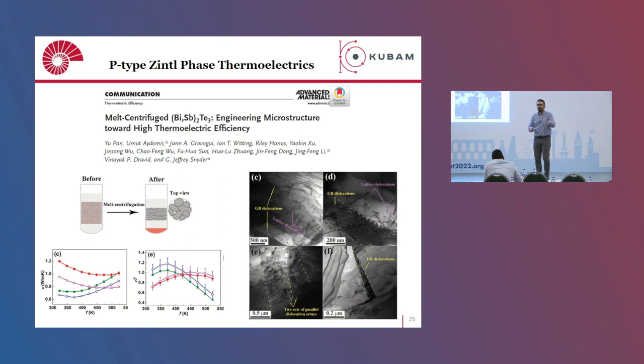So we knew that you can make this material p-type, but then we thought, how can we improve the thermoelectric efficiency, or what else can we do? So we applied what we call a melt centrifugation method to this material. We used this technique on bismuth antimony telluride, which is actually the best low-temperature material. The idea is that you intentionally add an element, for example tellurium, some excess tellurium, inside bismuth antimony telluride, and with a technique you remove this molten tellurium at high temperature. This could be done with spark plasma sintering. We put a little bit of excess tellurium inside, put the material in an oven at high temperature, then quickly took it from the oven, did the centrifugation, and removed the tellurium from this phase.